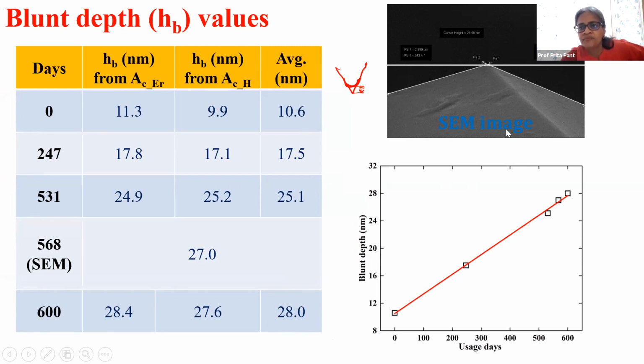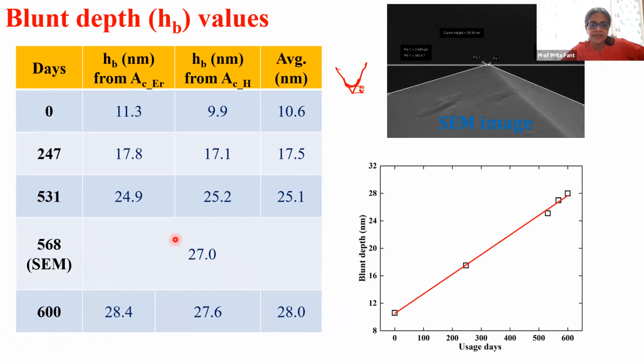I don't know whether you can see this very clearly, and it doesn't allow me to zoom in, but right here is where he's been able to estimate this blunt depth from his SEM image. And if you see that, it came out to be about 27 nanometers. So at about 530 days, we had estimated about 25 nanometers. This is 27. In 600 days, we were at about 27, 28. So we think what we are doing is sensible.